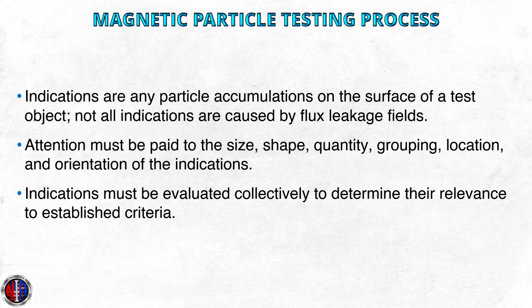Indications are any particle accumulation on the surface of the test object. Not all indications are caused by flux leakage fields. Attention must be paid to the size, shape, quantity, grouping, location, and orientation of the indications. Indications must be evaluated collectively to determine their relevance to established criteria. Proficiency in this area comes with experience.